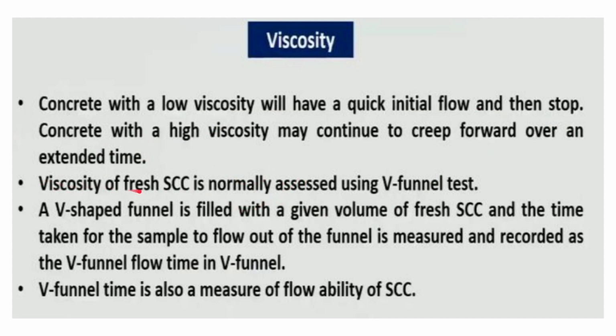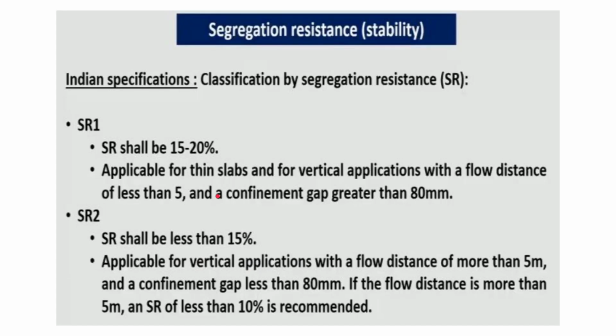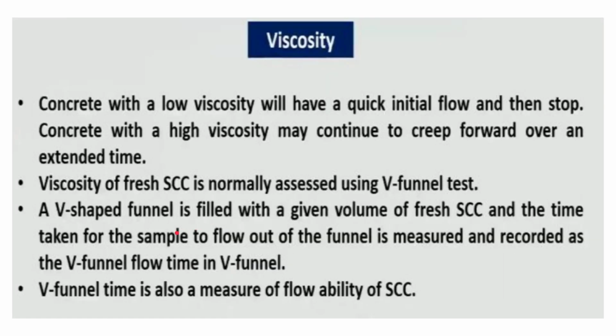The viscosity of fresh SCC is normally assessed using the V funnel test. As I mentioned, there are basically four tests. The filling ability, mainly the flowability, was done by the slump flow test. Second was the passing ability, which was mainly done by the L box test. Third was the segregation resistance or stability, which was mainly done by the sieving test. And the last is the viscosity, which is basically done by the V-shaped funnel test.